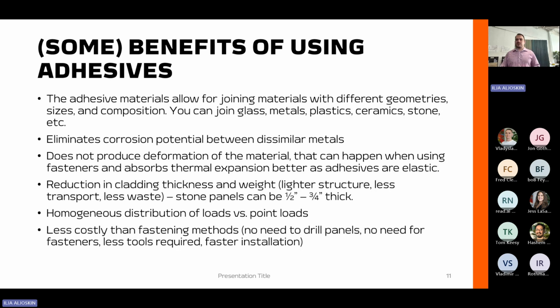It also does not produce deformation of the material that can happen when using fasteners. And the adhesive absorbs thermal expansion because adhesives are elastic. So as the substrate moves, as the cladding panel moves, it moves with it because it is elastic. And with screws, you have to be very careful. For example, you have to have fixed point connections, flexible point connections, and you have to make sure that your screw is in the center of that slot or the oversized hole when you're attaching cladding. And we've seen a lot of failures happen in other projects or just in the industry in general because this is not followed. If you're using adhesives, you don't have to worry about it as much because the adhesive allows for this elasticity to happen.